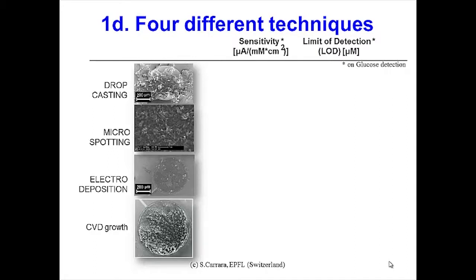Of course, we can keep just the glucose detection as an example and compare sensitivity and limit of detection, technology per technology. In the first case, we obtain 27.7 micro-amps per millimolar per centimeter square. While, for example, with the micro-spotting, we obtain only 0.46, almost 2 orders of magnitude in difference between the two technologies. This is mainly due to the fact that we are less efficient in the number of carbon nanotubes that we succeed in transferring on the platform, and that we have, don't forget, the polymer that of course hides part of the carbon nanotube surface. The decreased sensitivity, of course, reflects in a worse limit of detection, so our sensor is more blind.